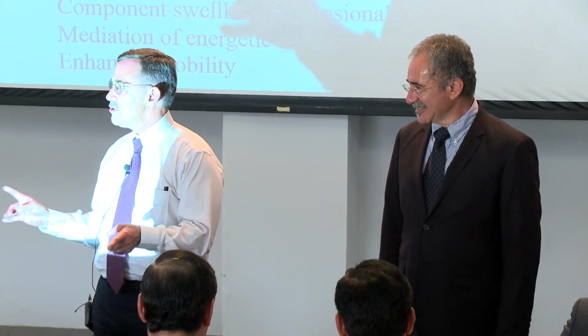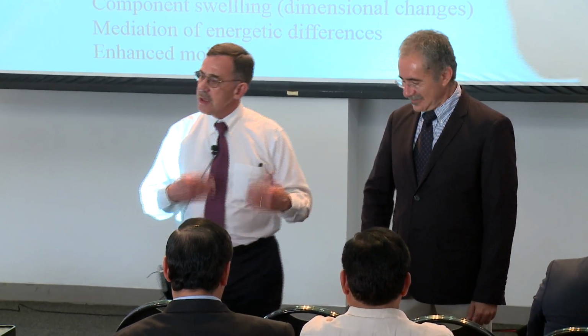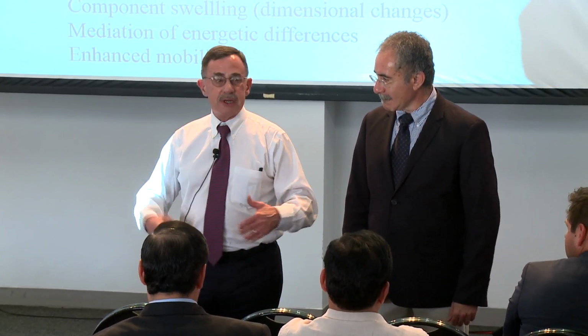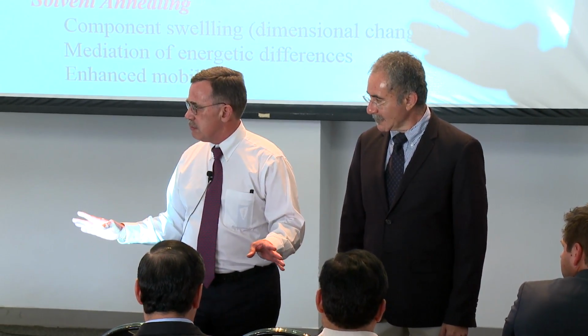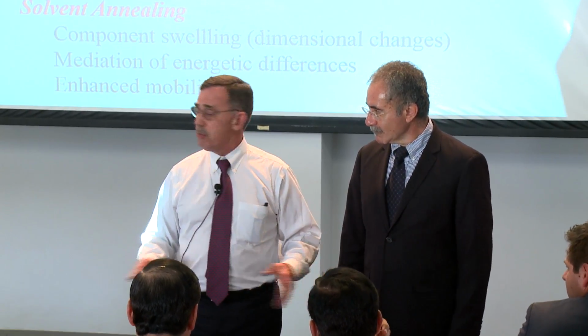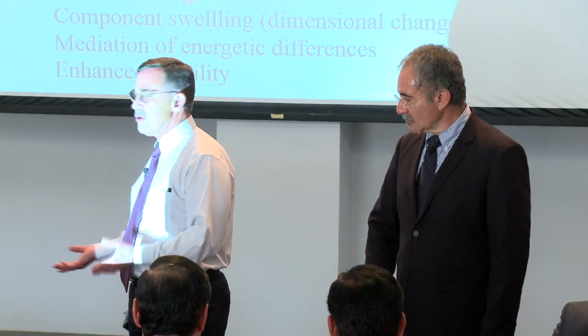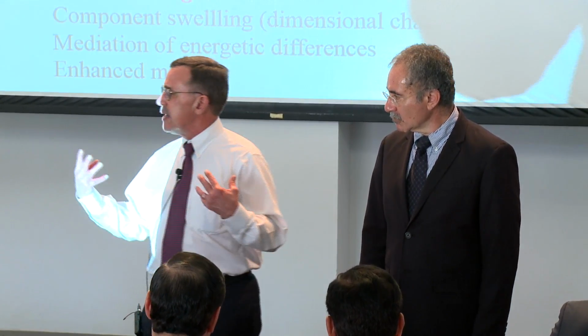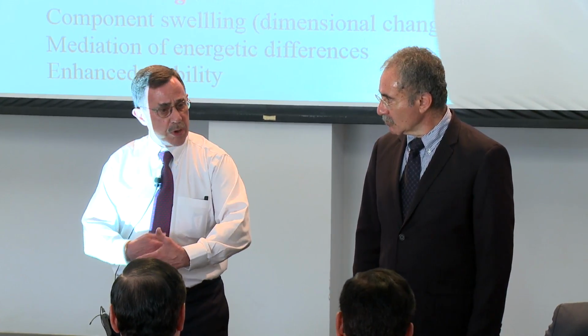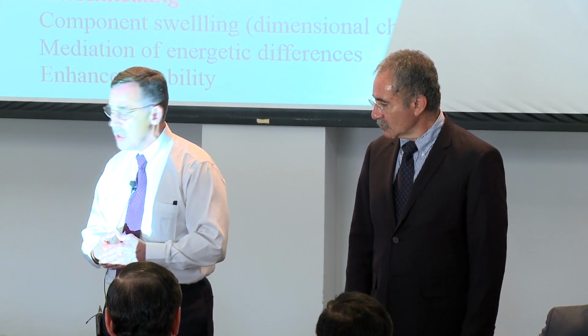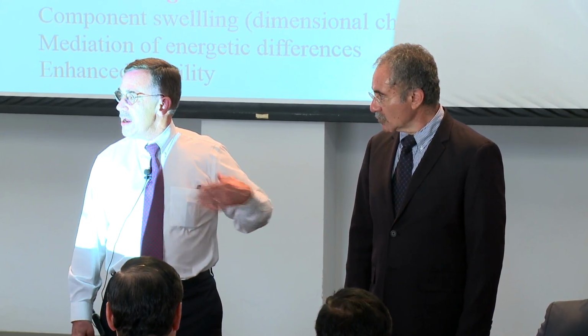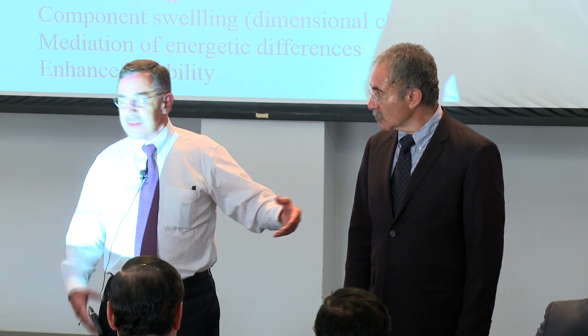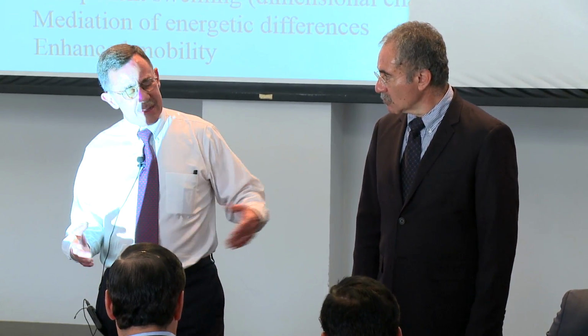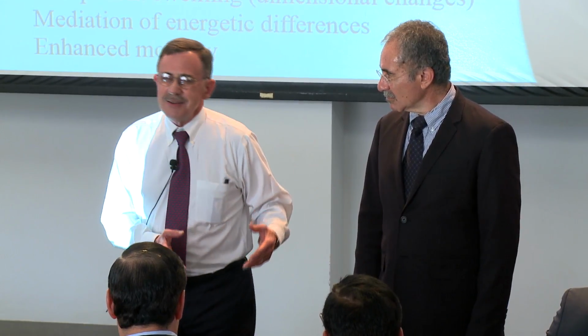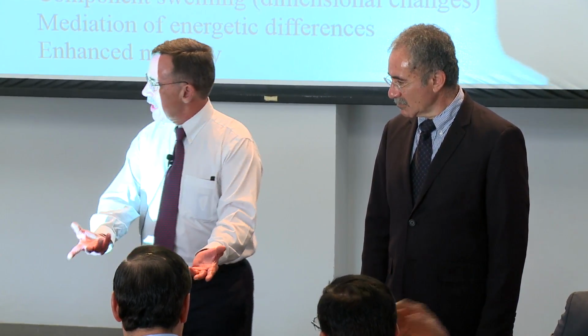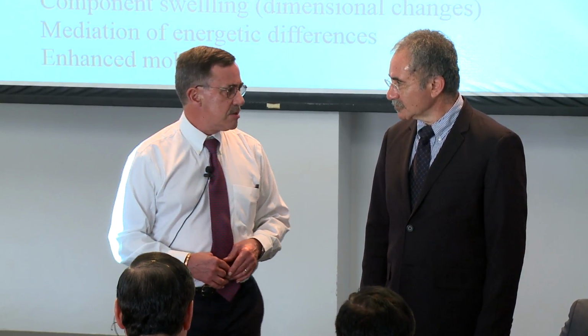Now, I just showed you something really simple. By controlling interfacial interactions, I can control the orientation of materials at the surface. Trivial to do. I can take a surface and treat it beforehand, spin coat a film, heat it above the glass transition temperature, things move around, and I can control the orientation. I can also help controlling the orientation by controlling the thickness of the film. Because if the film happens to be commensurate with our size, then I put no frustrating forces on the film. But if the film happens to be a little bit thinner, we start to get squeezed. And so that helps me in terms of controlling the orientation.